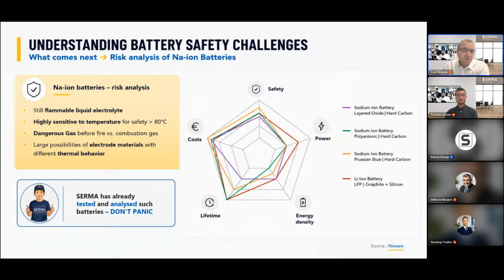And also something very important in your risk analysis for sodium-ion battery is that you have very large possibilities of electrode materials with different thermal behavior. We have seen that for lithium-ion batteries, you have NMC, LFP, which are the most well-known. But for sodium-ion, you have many more possibilities, which means that every material has a different thermal behavior and can behave differently. So this is why it's very important to test sodium-ion batteries as well. And at least at SERMA, we already tested quite some, and we don't always have the same results depending on the chemistries.